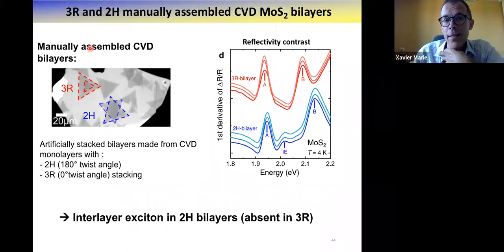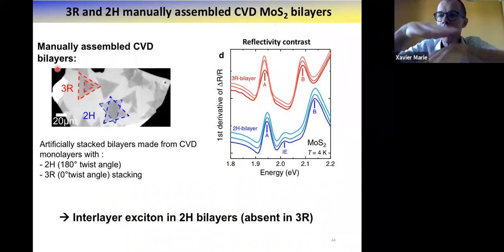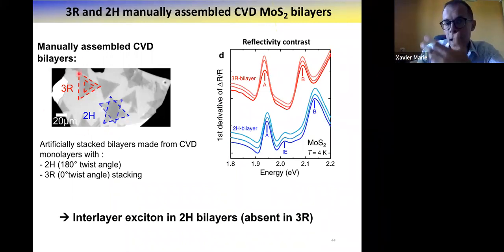One way is a manual assembly of CVD bilayer. So basically you have different monolayers obtained by CVD, and you just remove one layer, you stack it on the other, and you control the angle, 180 degrees or 0 degrees. And so you can fabricate again the two bilayers, the 3R stacking and the 2H. And again, you see in the 3R bilayer in the reflectivity experiment, A exciton, B exciton, nothing between. Whereas for 2H, again, a clear signature, a clear signal of the interlayer exciton.